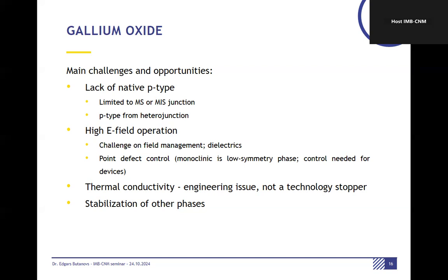Other issues are, of course, the challenge of field management, so selection of specific dielectrics for gallium oxide, as well as point defect control, which I think is now a bit more understood. Monoclinic is a very low symmetry phase, so there can be a lot of different defects, and they appear there quite easily. As a grower, I know how complex it is to grow very high quality gallium oxide.